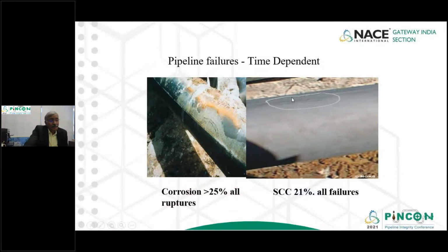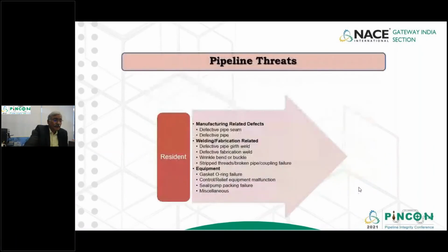So if you see here, of the pipeline failures that are time dependent, 25% are because of corrosion, and 21% of the failures have been seen because of stress corrosion cracking, which has been observed in some parts of the globe. Come to the stable, or resident, defects.